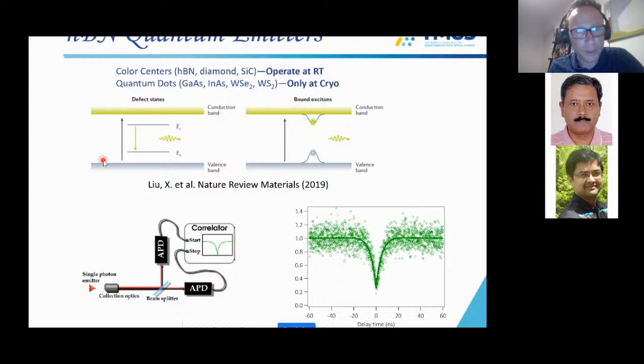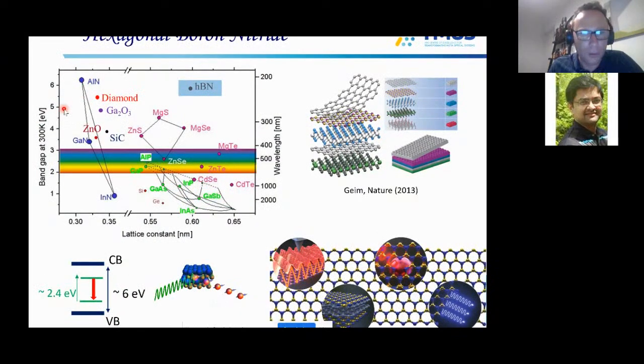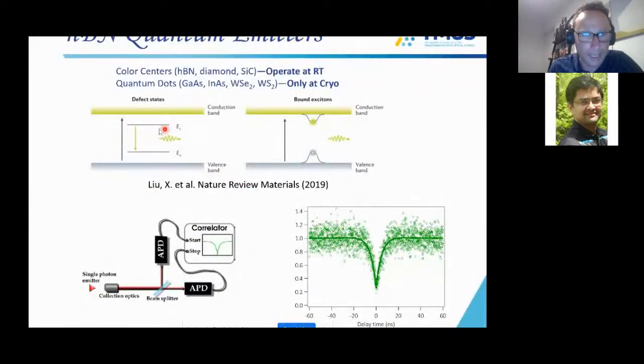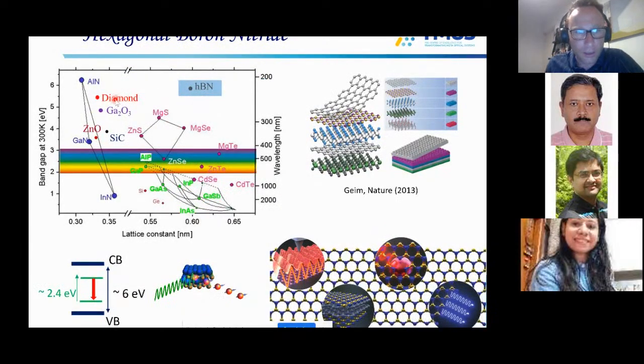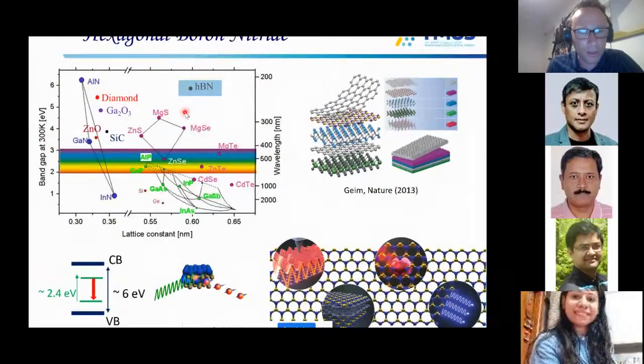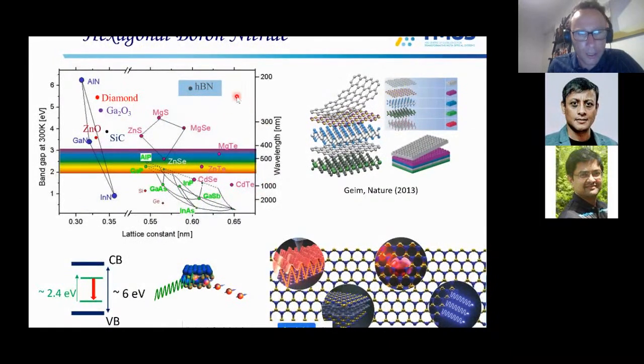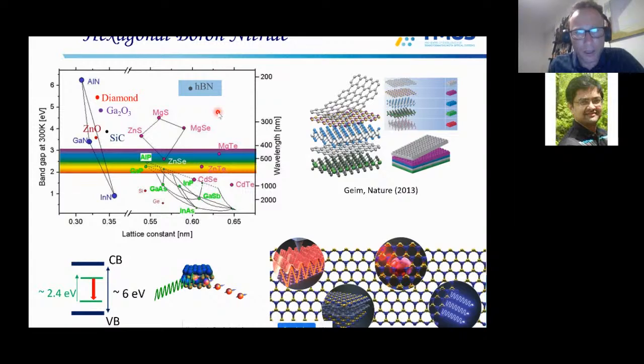So we're interested in the defect systems, and for that, of course, you need a wide bandgap material. If you look at this diagram of bandgap as a function of lattice constant, you will see that there are a few systems up here with a very high bandgap. Large bandgap is needed because you really want to have your ground and excited state very deep within the gap. You don't want to interface with any of the conduction or valence bands. Here is diamond, of course, studied for many years. Aluminum nitride is here as well, but also hBN. In this regard, hBN is unique because it is the only material out of this entire library that you can exfoliate into a two-dimensional system. And so our group and many other groups realized that a few years back, and started to study this hexagonal boron nitride for quantum photonic applications.